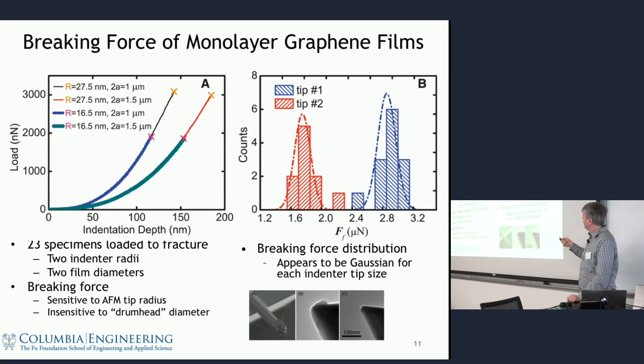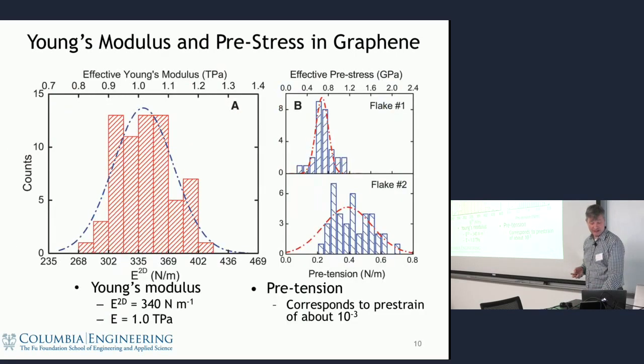So what we saw is that when we drove these films to failure, this is kind of 4 representative plots here. These little X's are the points where the films break. And what we saw is that the fracture force, the fracture load, depended only on the radius of curvature of the tip. These two curves are for different size membranes. A smaller diameter gives us a steeper force displacement response, but it fractures at the same point with the same type of tip. On the other hand, if we use a blunter tip with a larger radius, we need a larger force to fracture.